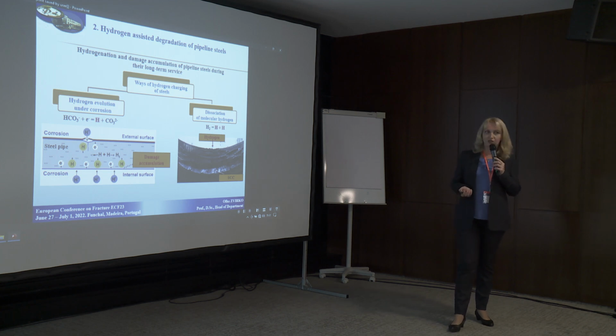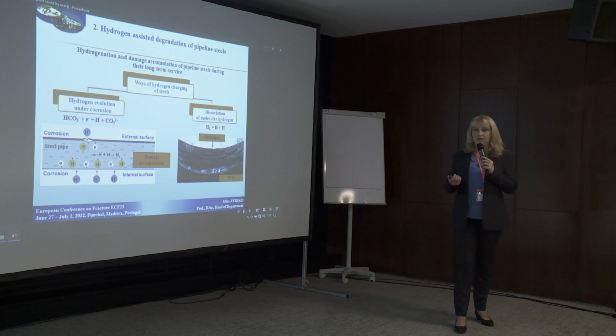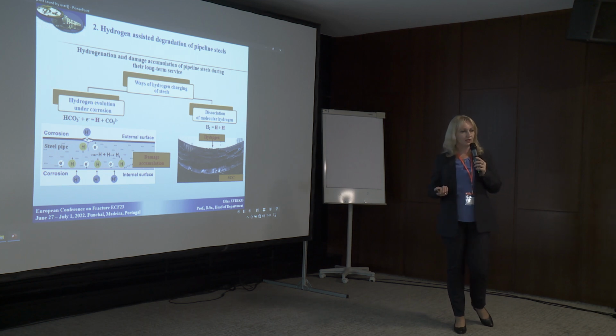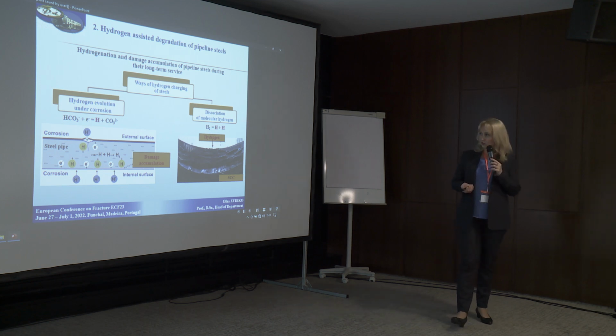The pipe can be hydrogenated from the inside and outside of the pipe due to electrochemical corrosion. What's more, at hydrogen transportation, it can also be evolved due to molecular hydrogen dissociation, especially on the fresh surface formed under deformation, for example, under cyclic loading. So a long-term mutual effect of corrosion, hydrogen charging, and working stresses facilitates formation, evolution, and accumulation of damages in steel at the nano and micro scales.